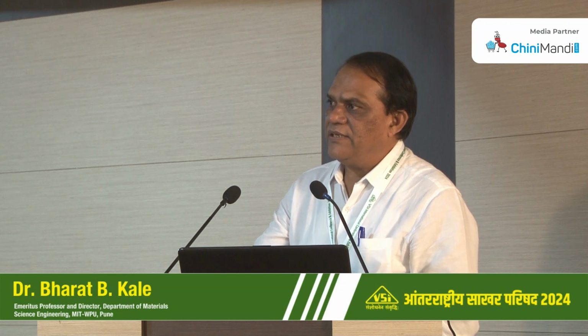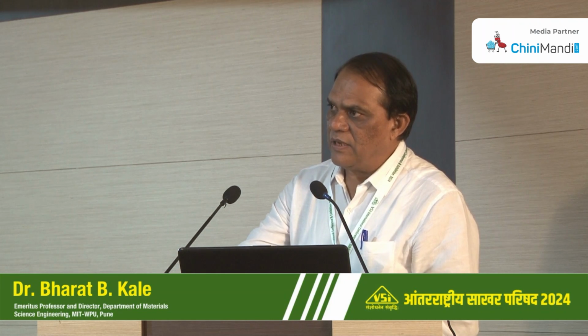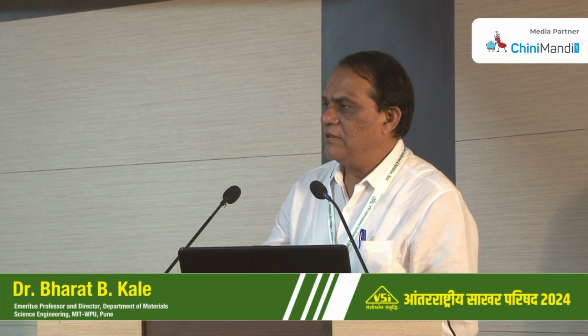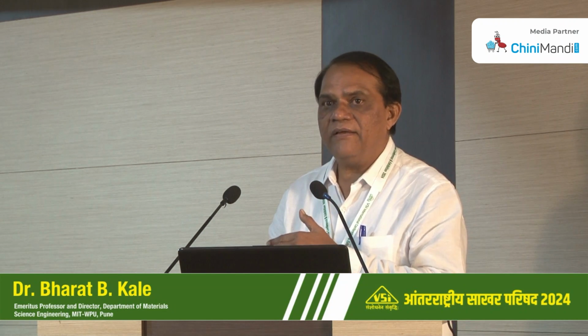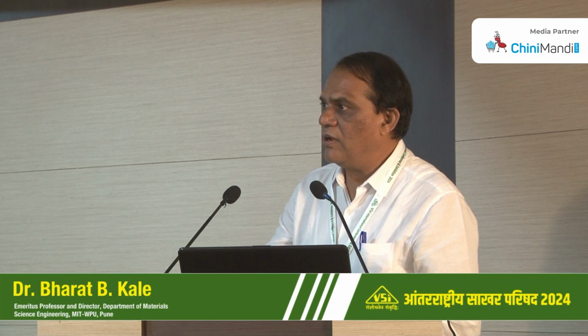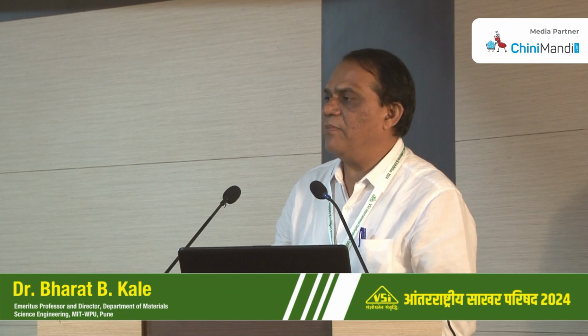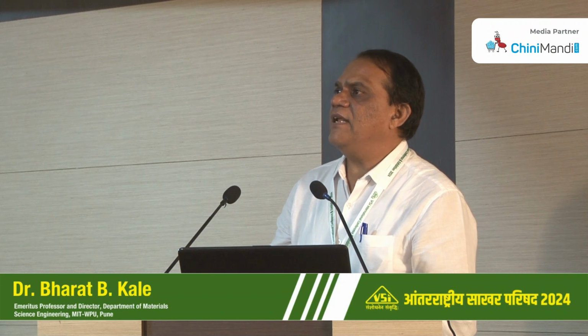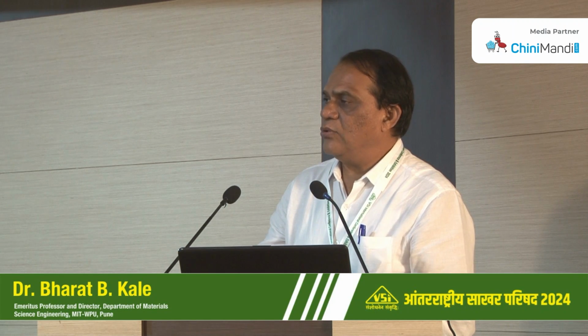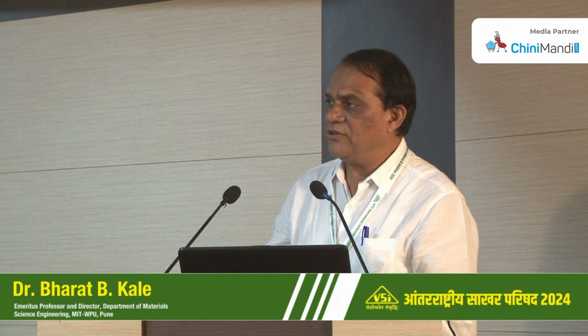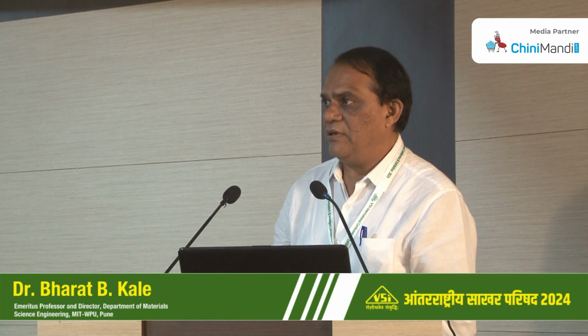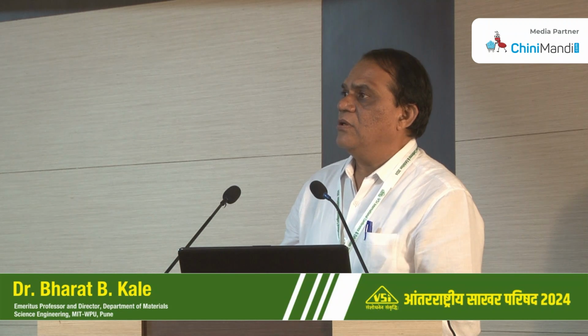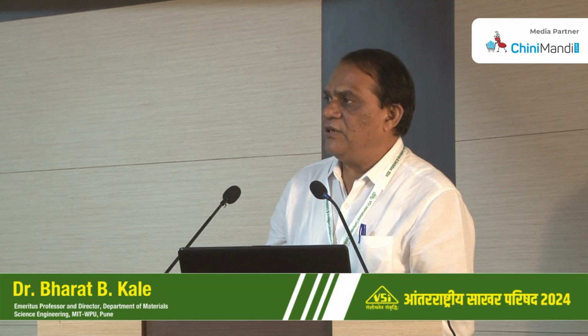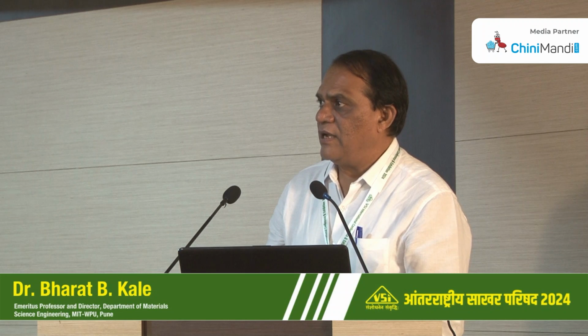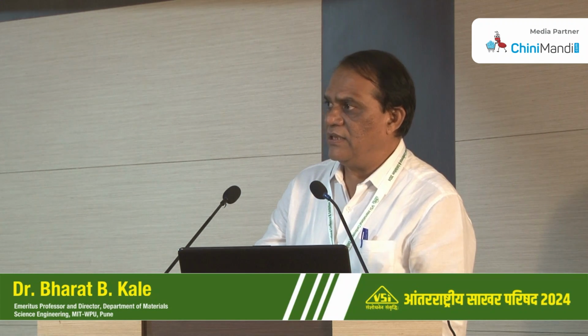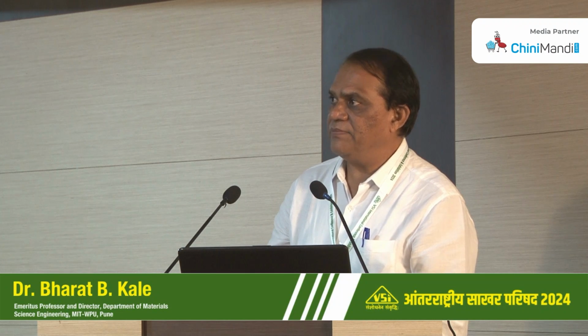So you can see the absorption is up to 800 nanometers here, and the growth in this glass is much higher as compared to silicate glass. You can go up to 12 nanometer in this type of glass. Very scintillating colors, yellow color, then brown color and black. Though you see the black color, the transmittance from this glass is much higher, 70 to 80%. So this is the CdS doped germanate glass. Again, we repeat it here, and you see the quantum dots in the glasses very nicely dispersed.